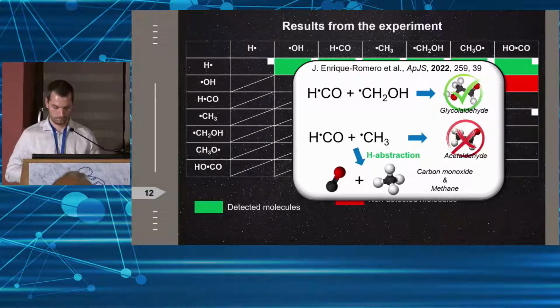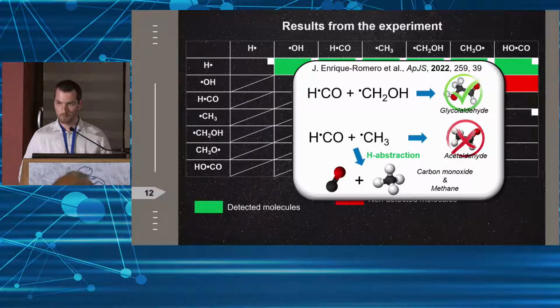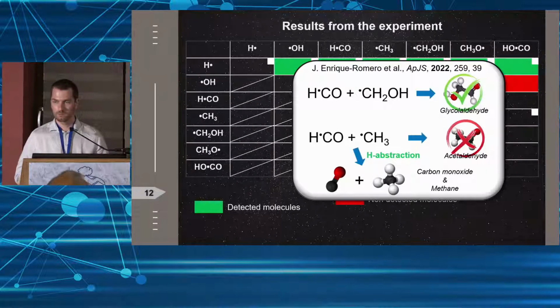And secondly, the reason why you don't see acetaldehyde in your experiment is because the infrared absorptions of acetaldehyde overlap with the infrared absorptions of the more complex molecules which you have. So you simply cannot see it, but you have it. In particular, the carbonyl functional groups are overlapped by the glycolaldehyde and by other molecules which have a CO functional group. So that's one of the suggestions when interpreting IR data of complex molecules. It doesn't always give the truth.